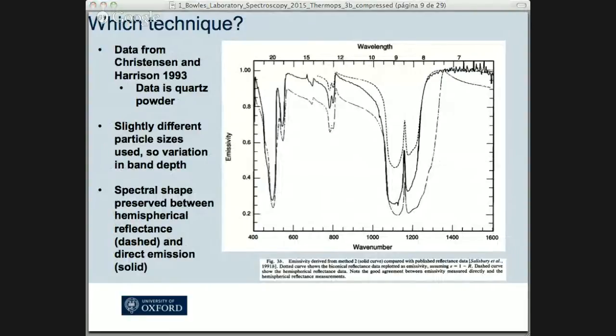So here's a rather confusing plot from Phil Christensen and Harrison's paper in 1993, where they compared the different techniques. This is slightly confusing because you've got different grain size distributions, but what they're trying to show is that the spectral shape, which is of course the important thing for getting the diagnostic features in the right places, for a quartz sample, is essentially preserved between directly measuring the thermal emission and the hemispherical reflectance method. So the integrating sphere method and the direct emission method give you pretty much the same answer.